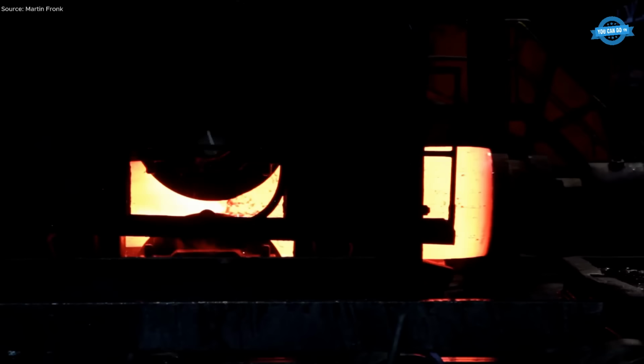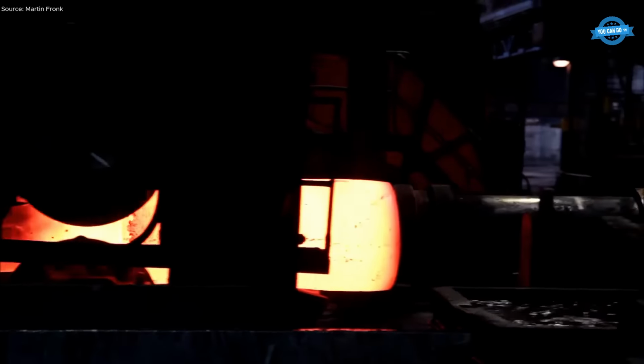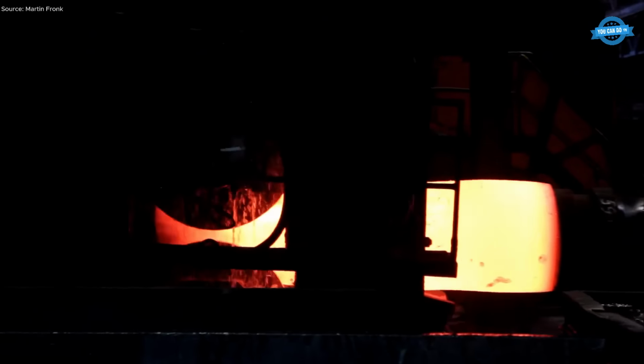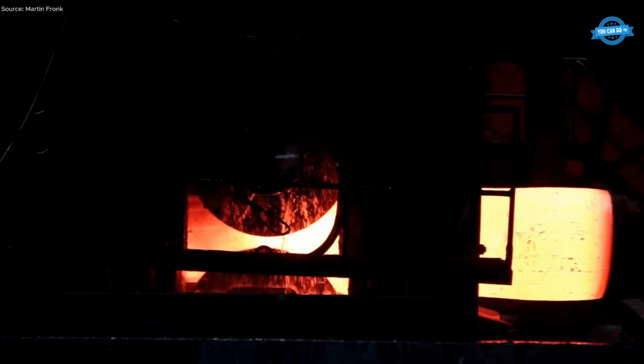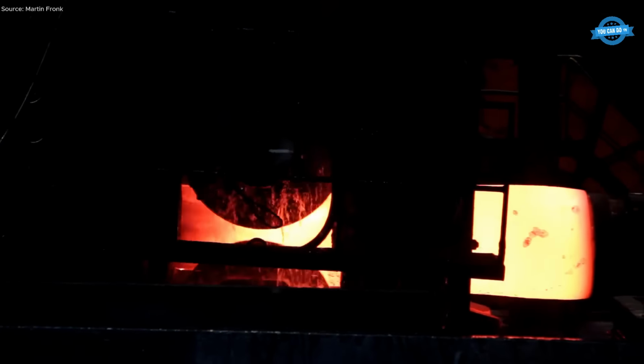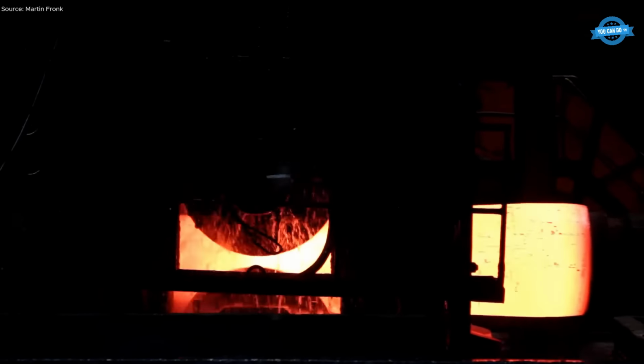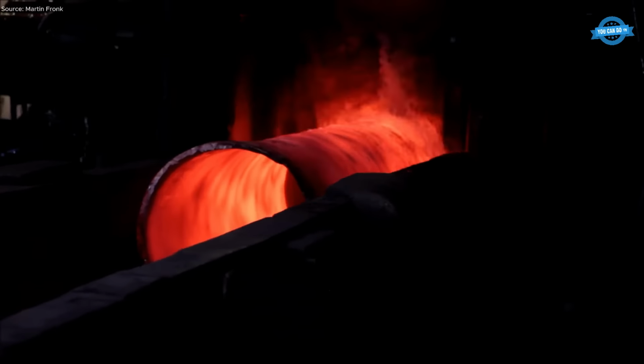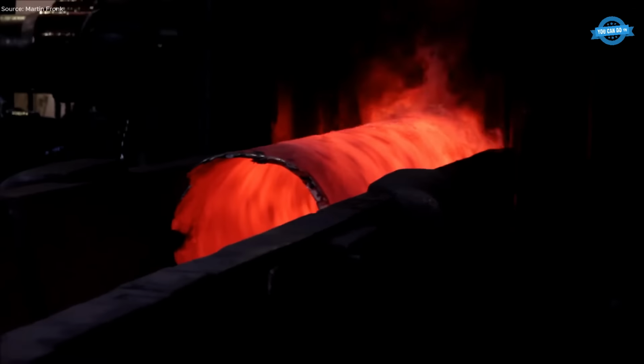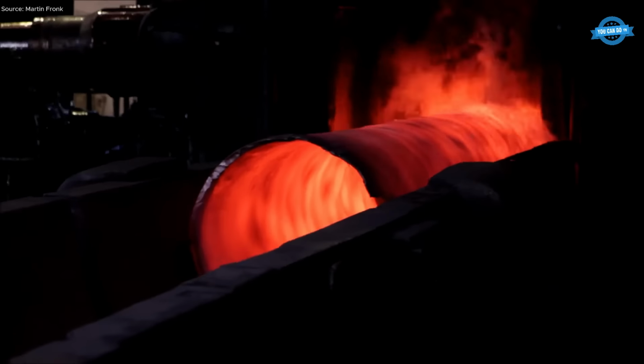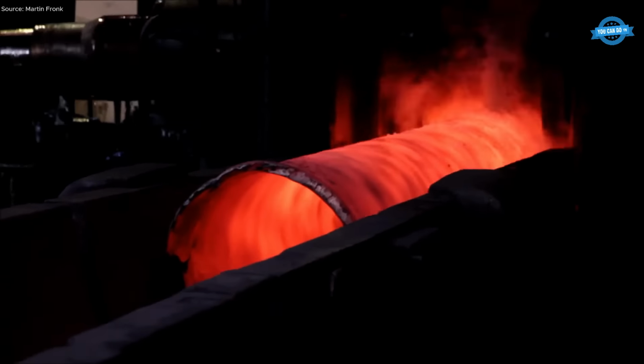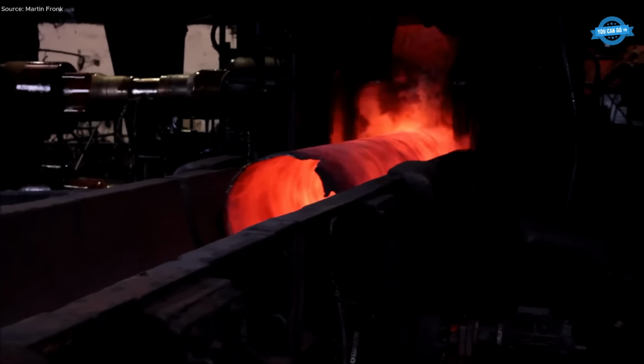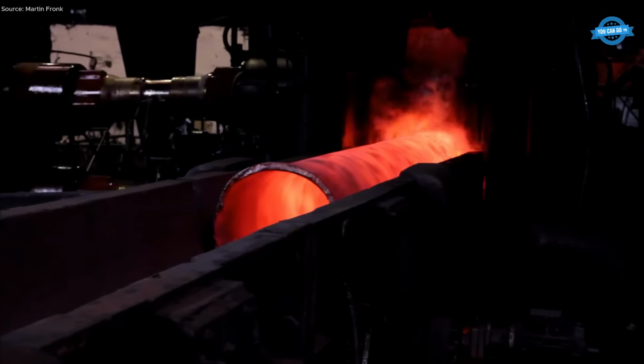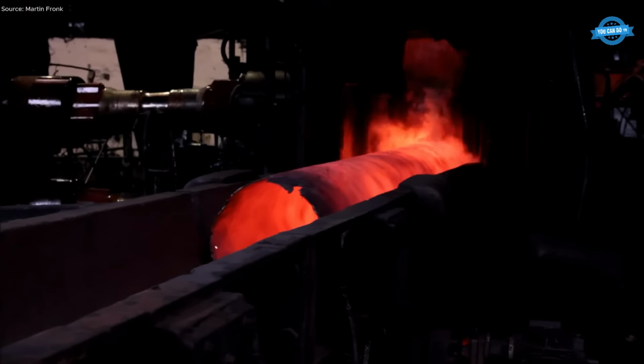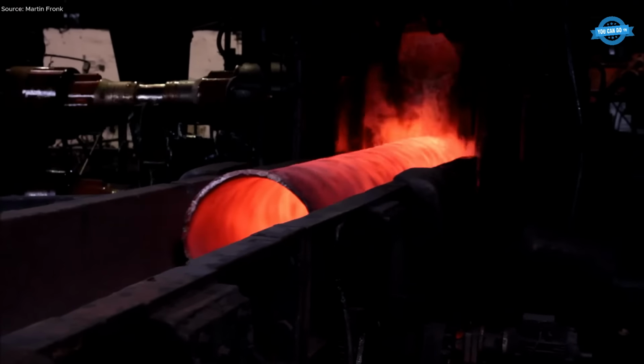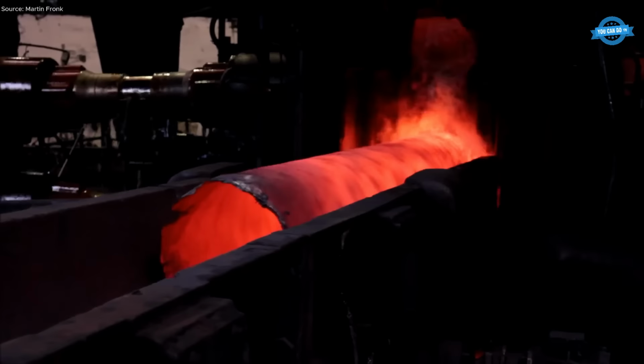The facility manufactures seamless pipes with outer diameters ranging from 273 millimeters to 660 millimeters and wall thicknesses between 9.5 millimeters and 72 millimeters, using various grades from carbon to high-performance alloys like P92. The rolling process employs the Mannesmann piercing method in pilger mills for hollowing and reducing cross-sections. High precision is achieved through standardized processing, supported by ISO certification and international norms.